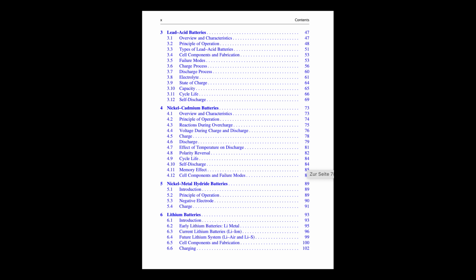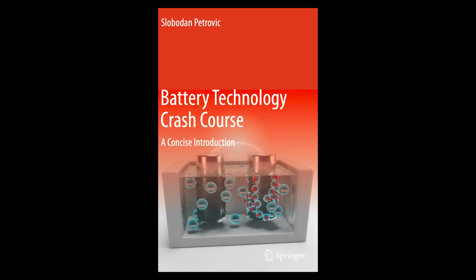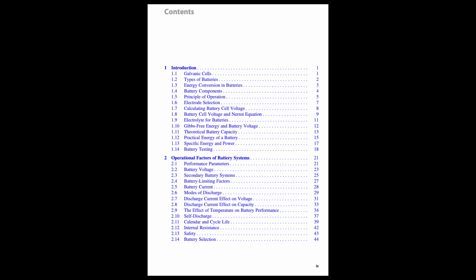Figure 4.1. Discharge. At the negative cadmium electrode, cadmium gets oxidized. It reacts with hydroxide ions from the potassium hydroxide, KOH electrolyte, forming cadmium hydroxide and releasing electrons. Cadmium to cadmium hydroxide. Yep. At the positive nickel oxyhydroxide electrode, that gets reduced. It reacts with water, takes electrons, and forms nickel hydroxide, releasing hydroxide ions back into the electrolyte.